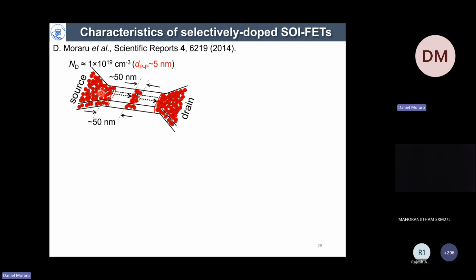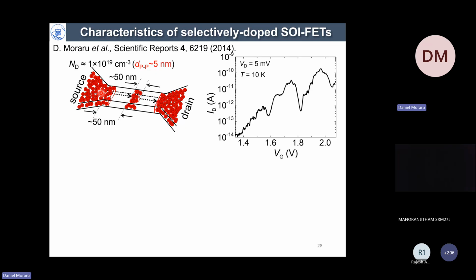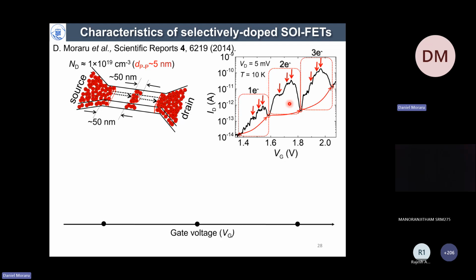So with this, we obtained the IV characteristics, again at low temperatures and small source drain bias, and they look significantly different from the ones due to single dopants. Now we observe current peak envelopes, broader structures, which are also an illustration of single electron tunneling. At the valleys of these peaks, electrons are captured into this quantum dot. However, there is also some substructure embedded into these peak structures, and this, despite the noise and a little bit of lack of similarity, we can ascribe to tunneling transport spectroscopy of the dopant molecule.